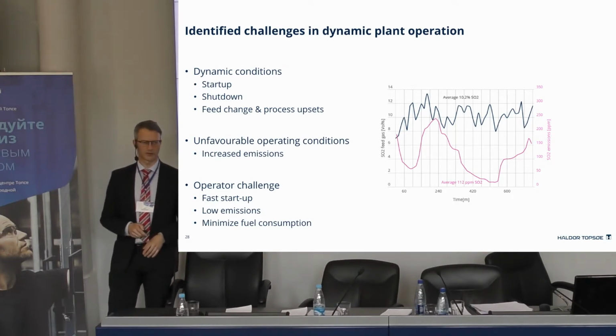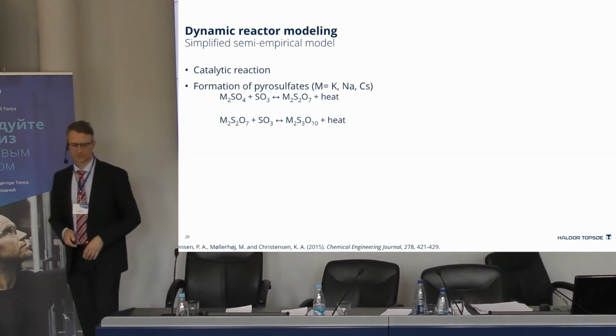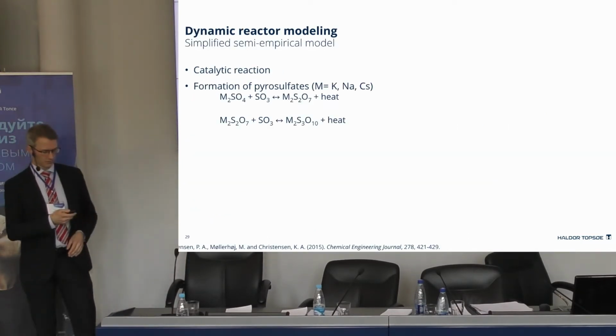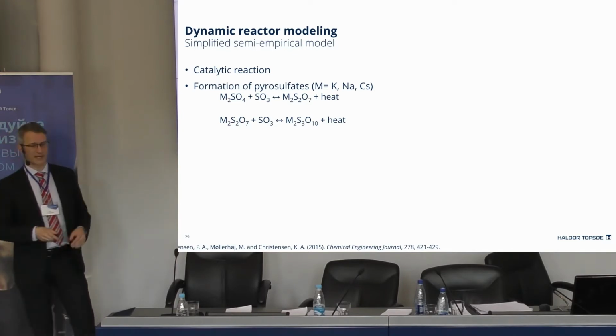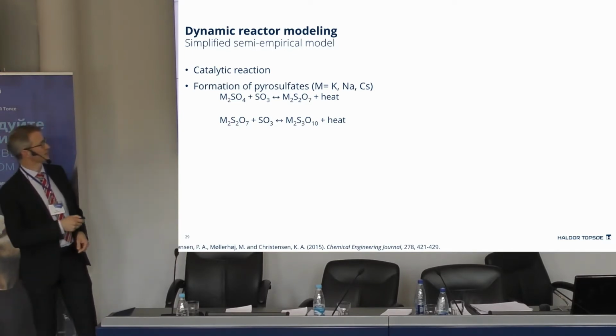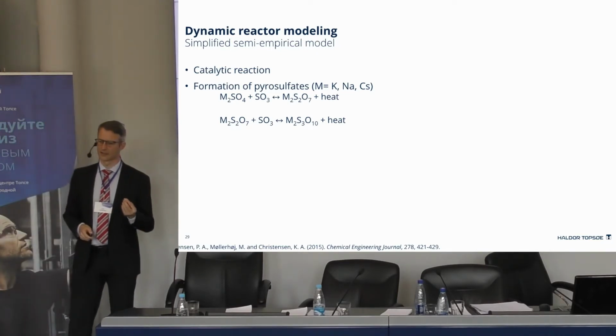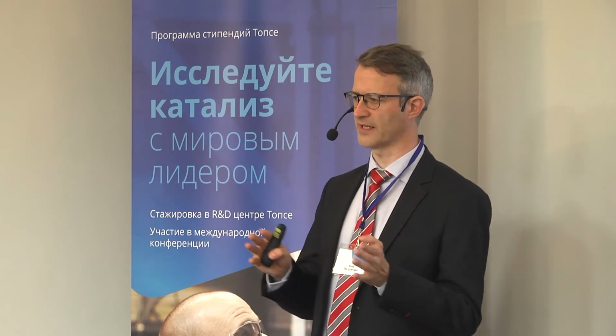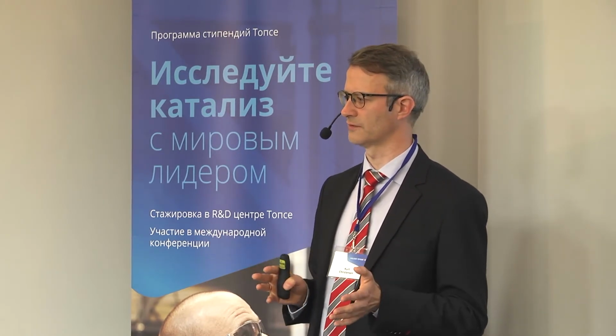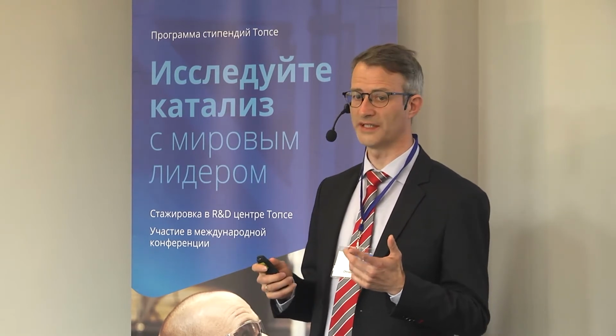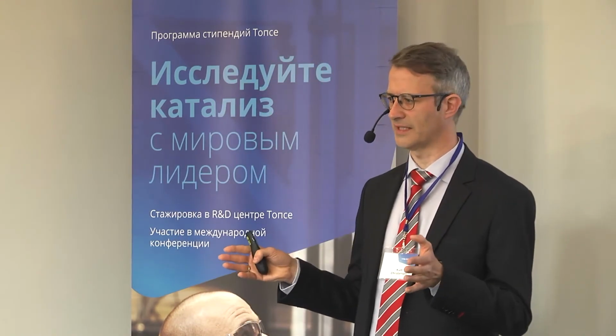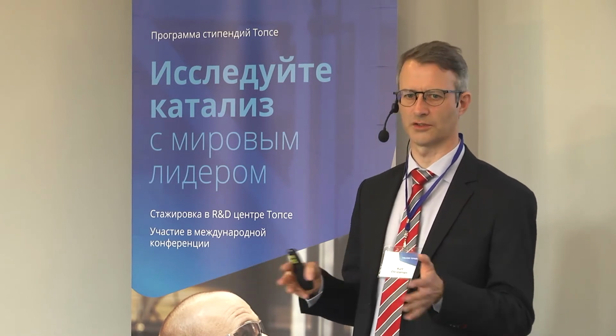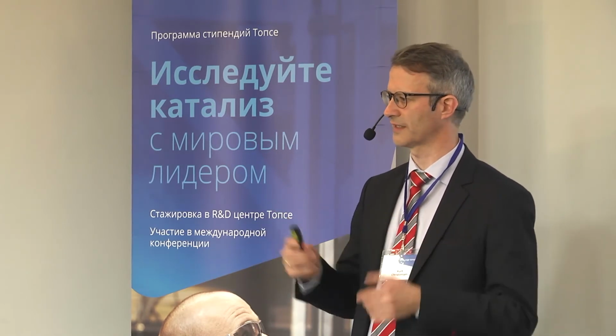So we've built a semi-empirical model for this, and in the model we want the catalytic reaction. That's of course the main thing, but then we also need the formation of the pyrosulfates, because that will have a huge effect on absorption and desorption of SO2 and SO3, and also on heat and heat waves in the reactor, because it's exothermic. And up to 10% of the catalyst mass may actually be absorbed and desorbed through these reactions. So it's a huge effect on the converter.